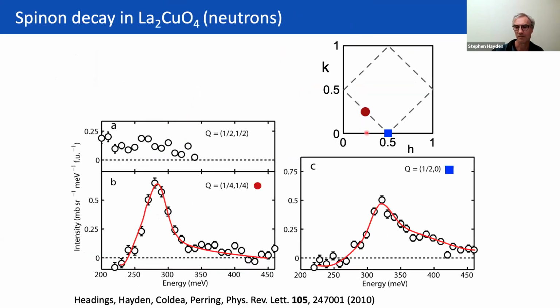Here's the falling apart of the magnons, what we call spinon decay, at this particular point here, the half-0. The magnon is broadened and has a much shorter lifetime, and this behavior seems to persist into the superconducting compositions. So here you can see the difference in the zone boundary magnon energy between these two points. It's higher at this point than this point.